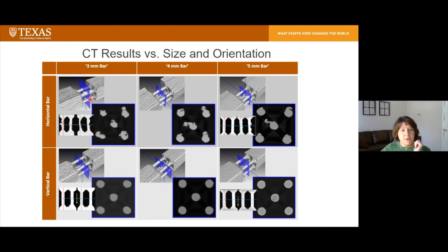So you can see that with these horizontal struts, it's very difficult for this metals machine to build those struts. So you see a lot of surface roughness, you see non-uniform cross sections as well. And then with the vertical bars, you see much less of it. You also see that it gets a little bit better as the bars get larger.